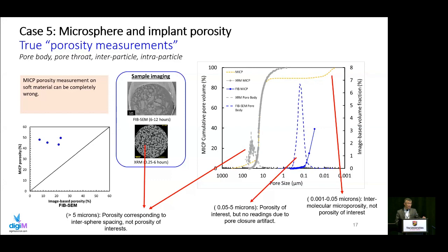Yeah, a lot of data on the right, it actually showed our image-based mercury porosimetry model. So it's still mercury porosimetry, but performed in silico using the 3-dimensional pore network. So that's this curve. And then with imaging data, we can not only characterize the pore network and the so-called pore throats, how they are connected, but also each individual pore body, which is this curve, right? Pore throats and pore body.